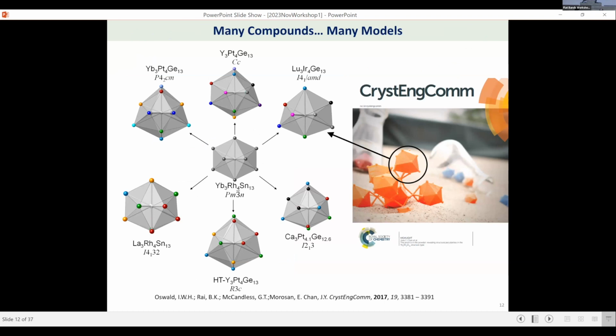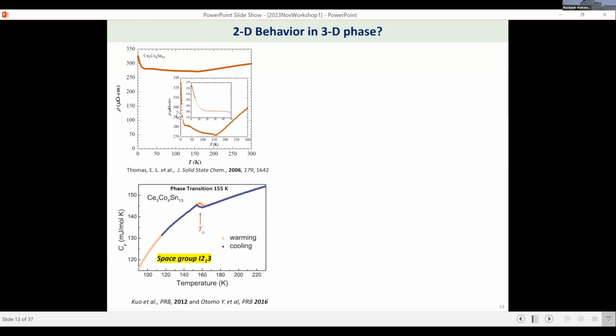And it turns out that not all the compounds are centrosymmetric, not all of them are cubic. Similar to the perovskites, depending on which elements, you can also have distortion. And that was intriguing to us, looking at the local environment again. This was in 2006, and we revisited this, looking at the literature, even in 2012 and 2016, we saw 2 reports where, in a 3-dimensional compound, you see a charge density wave. Coupled with this, there is a structural phase transition from centrosymmetric to non-centrosymmetric. That was exciting to us, because then the thought is, does that mean a charge density wave always requires a low dimensional entity?